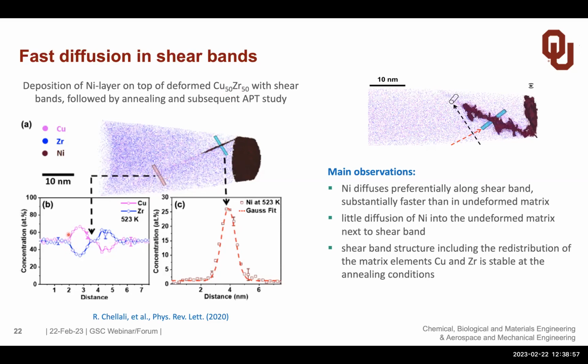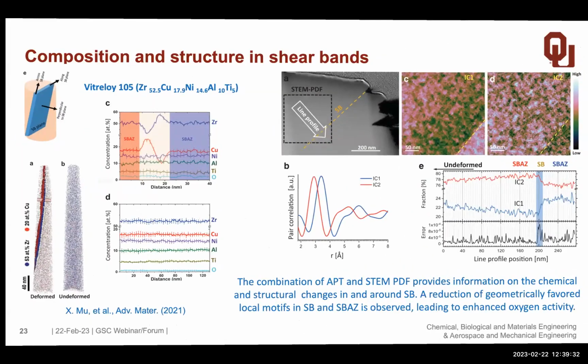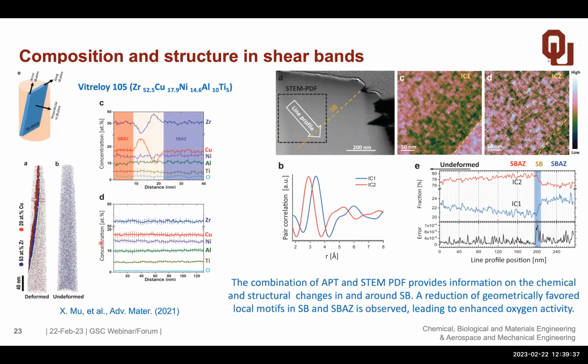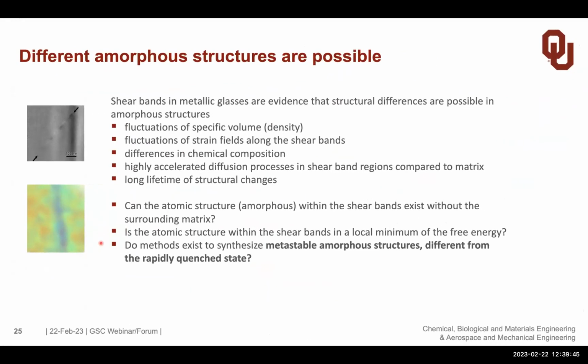You would also observe after this diffusion treatment that the composition profile of the copper and the zirconium, which occurs during the deformation, is maintained. There's enough mobility of the atoms to get rid of that kind of fluctuation, but it doesn't want to do that, which indicates that the system wants to be in that state, okay? So there is a state in the metallic glass which is different from the rapidly quenched state, which is a favorable structure. And we have looked at that with other techniques, for example the radial distribution function technique, and we found many details of that. I want to jump over that for time reasons. So we have indications in the shear bands of metallic glasses that there are differences in the atomic structure, which could be a stable new approach.